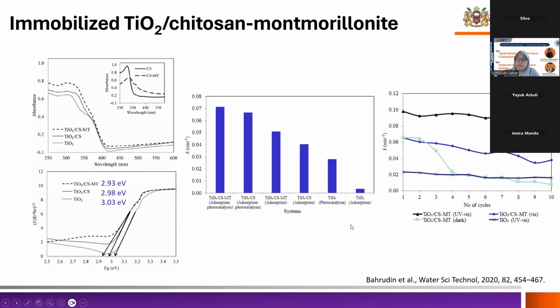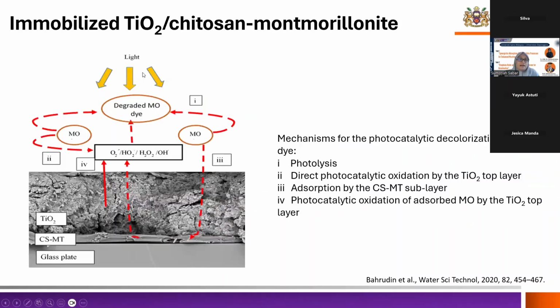So this study was conducted using a methyl orange dye. And these are the mechanisms for the degradation of the methyl orange. Okay, so the first one is the photolysis of the methyl orange, because methyl orange is sensitive to photons, and so it also undergoes photolysis. The second one is the direct photocatalytic oxidation by the TiO2 top layer. So this is the cross section of this layer by layer under scanning electron microscope. So you can see that this is the TiO2. And then this is the chitosan montmorillonite, and then this is the glass plate.